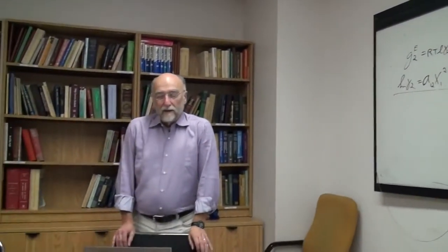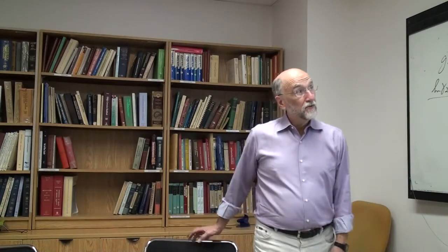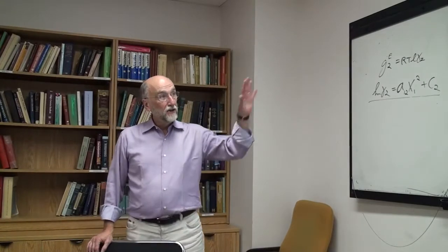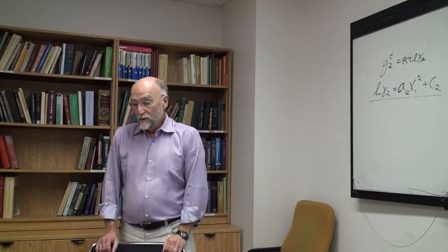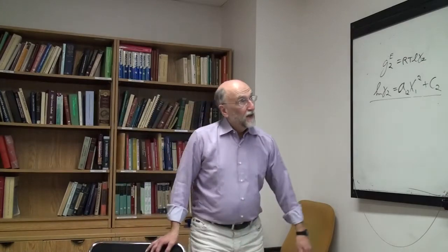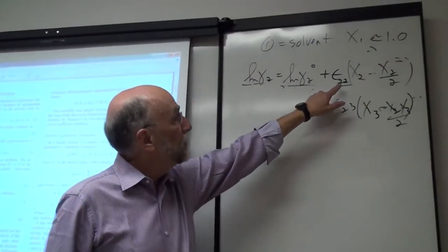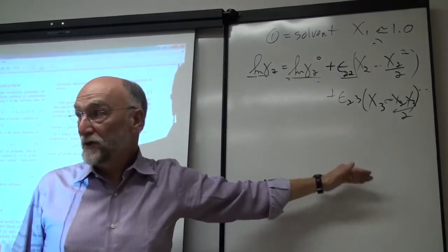And in the FactSage database, model type number 2 is the interaction parameter formalism. So you can use the interaction parameter formalism in the FactSage database for dilute solutions. In fact that is used for dilute liquid iron solutions, for example. Dilute solutions of various things in liquid iron use the Wagner formalism. This is model number 2 in the FactSage database, in which the coefficients that you enter are the log gamma Henrians. You enter log gamma 2,0, log gamma 3,0, log gamma 4,0, and the interaction parameters epsilon 2,2, epsilon 2,3, and so on.